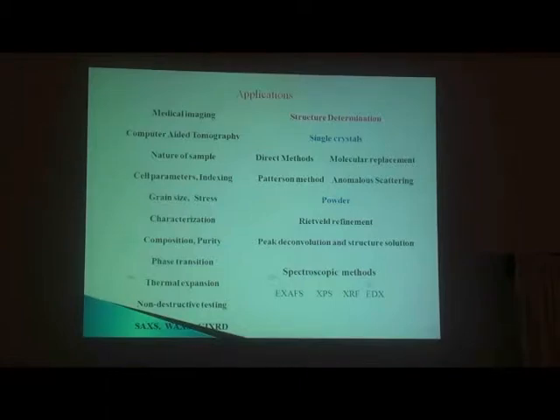When you have powder, you have the Rietveld refinement technique. What is the Rietveld refinement? It's just a refinement. You know something that exists and you have data. And you know that your data is going to be relevant to some particular system, for example barium titanate perovskite structure. You modified it with some phase. You know that a little bit of deviation you can expect from the actual barium titanate structure. Then you know that information from chemistry or some intuition. Then you put that value in, do the recalculation and check with the data, and if there is agreement, you say that this is perfect. That's only a refinement technique.